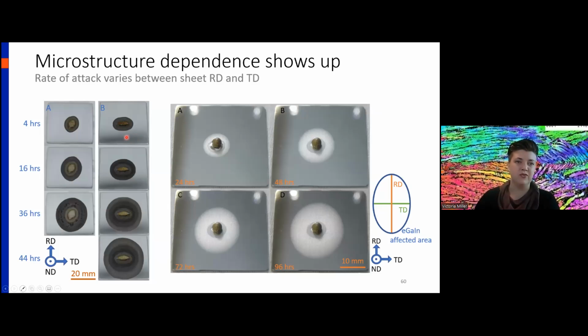And to prove this is true, to prove to ourselves, we started with an elongated droplet, a droplet elongated in the transverse direction. And at the end of this oxidation exposure, not only did the rolling direction keep pace with the transverse direction, it actually outpaced it. So regardless of the morphology of your starting droplet, your rolling direction propagation goes faster.